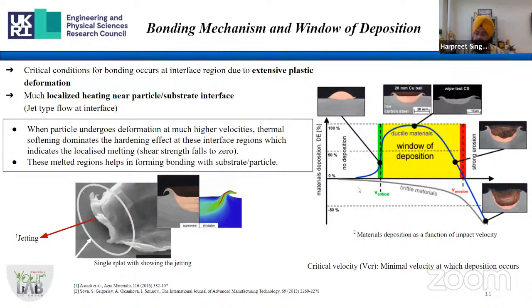Now this deposition, in fact this whole coating formation, depends on the velocity of the particles, because velocity will dictate how much energy we are going with, which will help us to deform on the surface. There we have seen that for each set of materials, that means feedstock material and the substrate, there is some critical value of velocity at which the particle will start sticking on the surface. It's not that you will propel them towards the substrate and they will stick. There has to be some threshold value beyond which it will help you to retain the particles on the substrate, right?